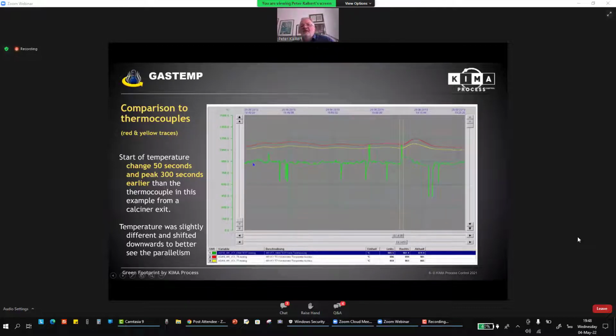By the way, you see that the temperature shown in the green trace differs from the temperature shown by the thermocouples. This is mainly due to the fact that the thermocouples are much closer to the flame. And as I mentioned, you see not only the temperature of the gas, but also the temperature of the flame. Also, we have shifted the green trace a little bit down in order to make it more clearly visible what is happening here. And you see the reaction for a closed loop control could have been made nearly 5 minutes earlier than you would do with the thermocouple devices.